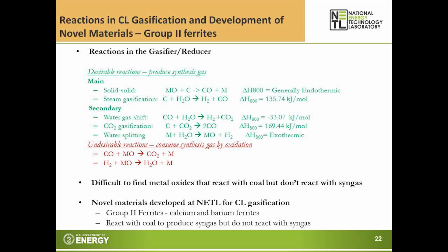It's very difficult to find the right oxygen carrier for the process. If you look at the reactions in the gasifier, all the desirable reactions should produce syngas. So these include solid-solid reaction, steam gasification, water gas shift reaction, CO2 gasification, and water splitting reaction. They all produce carbon monoxide and hydrogen. The undesirable reactions consume the syngas by oxidation. For example, metal oxides that we use for the oxygen carriers can react with carbon monoxide to produce CO2 or react with hydrogen to form water.